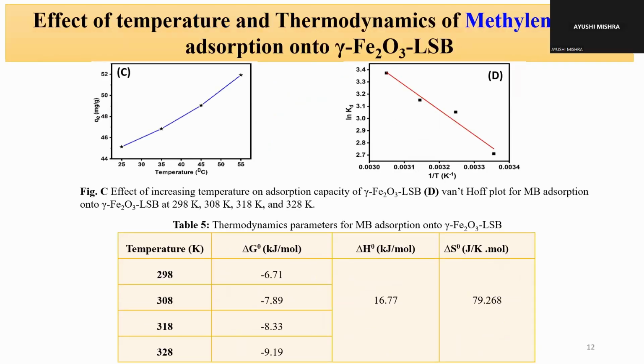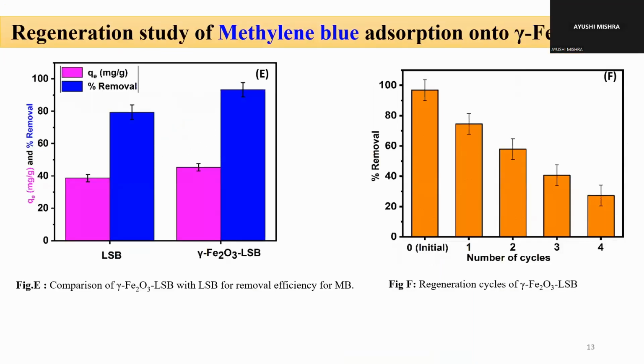After that, we also studied the effect of temperature on the adsorption process. As we can clearly see, on increasing the temperature, the adsorption capacity of the magnetic biochar increased, and we can also see the van't Hoff plot from calculating the thermodynamic parameters. We can see it's an endothermic reaction, and it is also spontaneous. We have also tried to compare the magnetic biochar with biochar only.